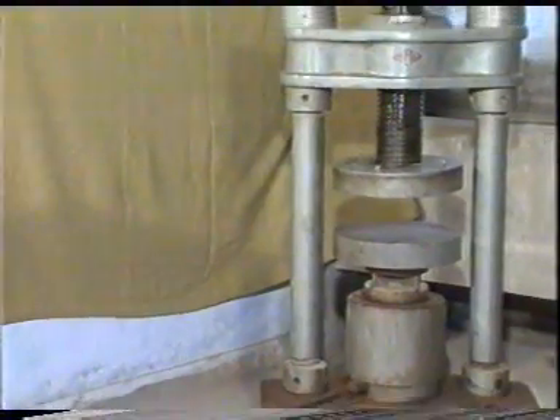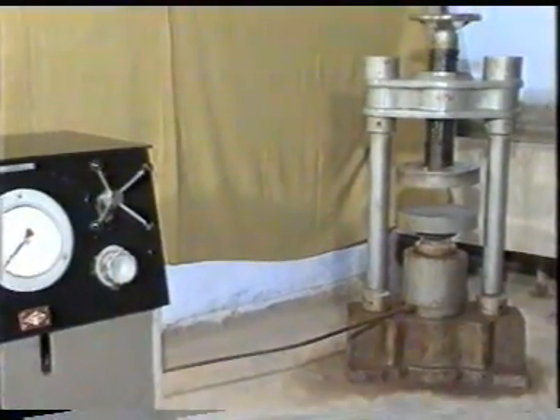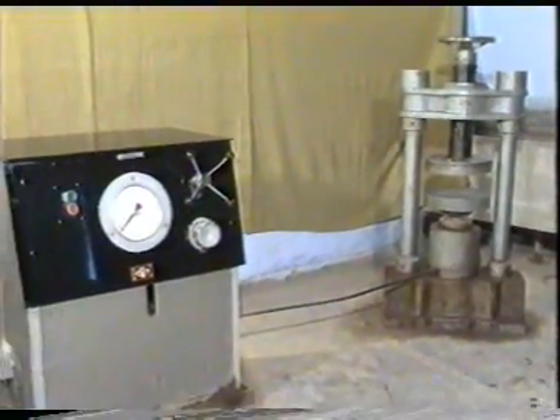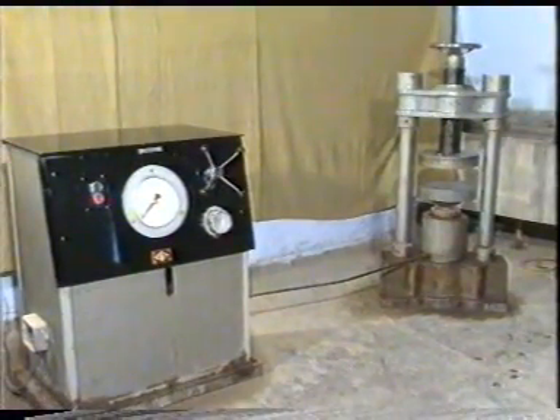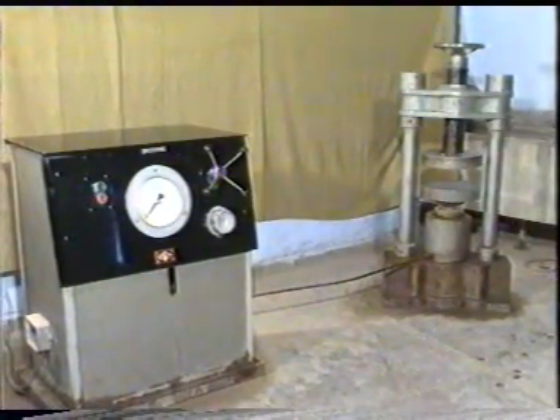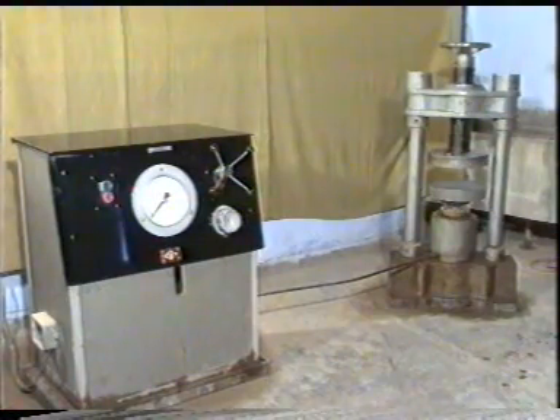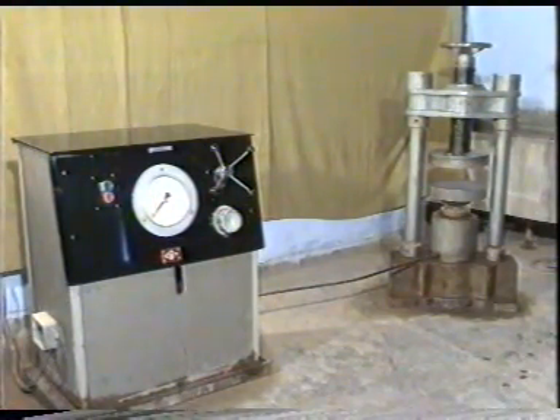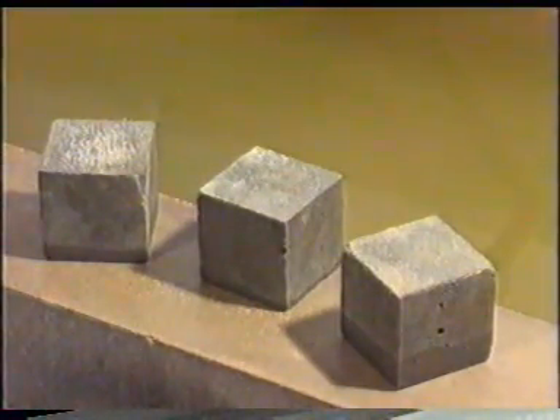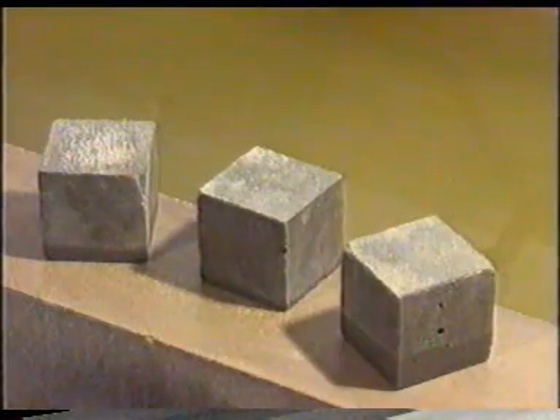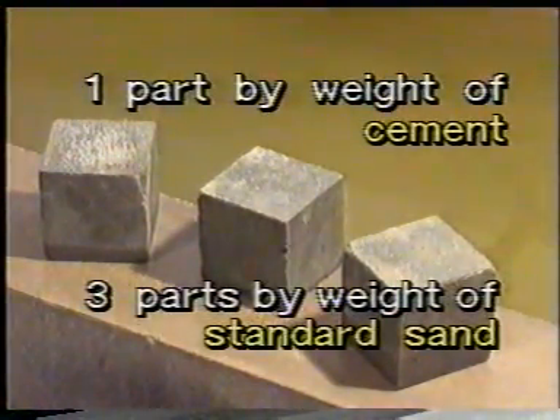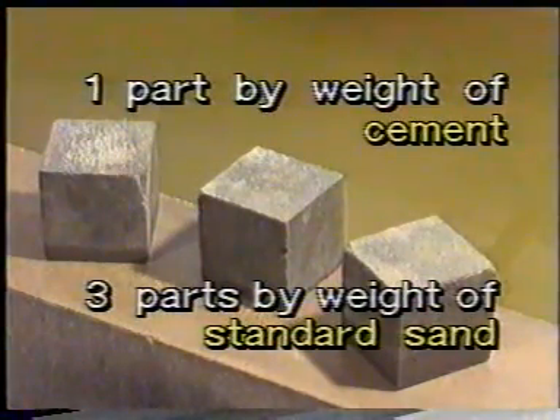Compression testing machine helps in determining the compressive strength of cement, which is an important check employed to determine the suitability of cement for preparing cement concrete. The compressive strength of cement is tested by cement mortar cubes prepared with 1 part by weight of cement and 3 parts by weight of standard sand.